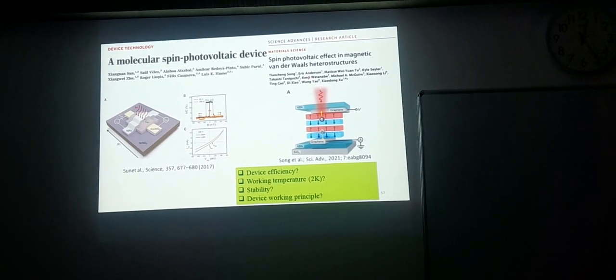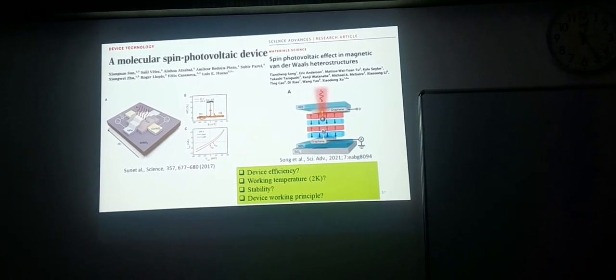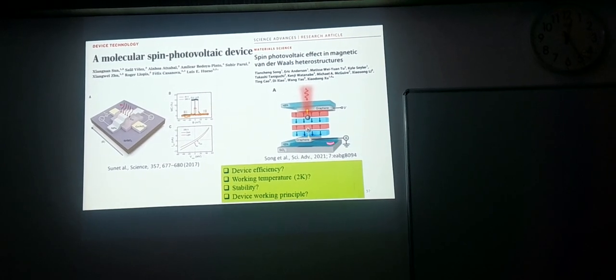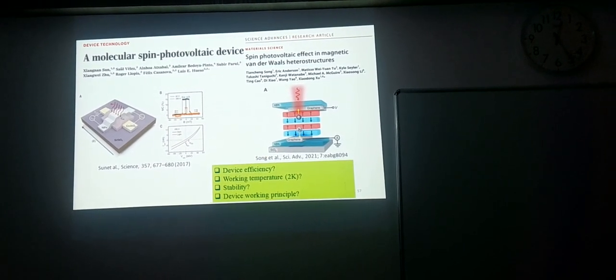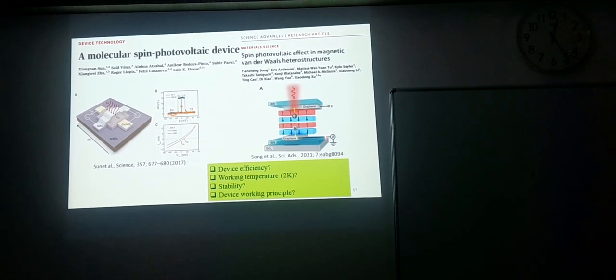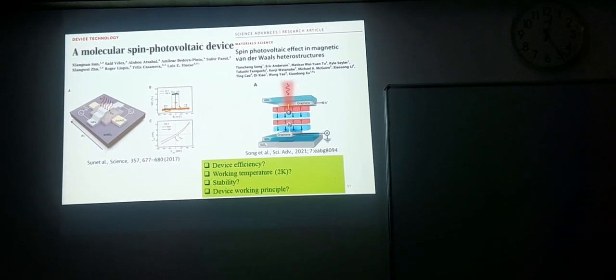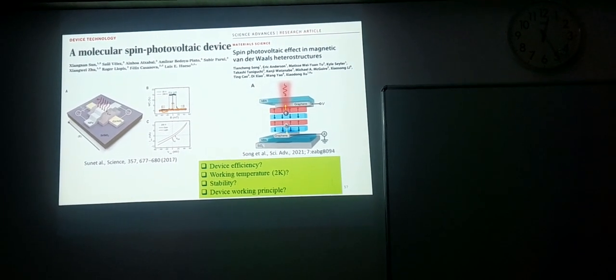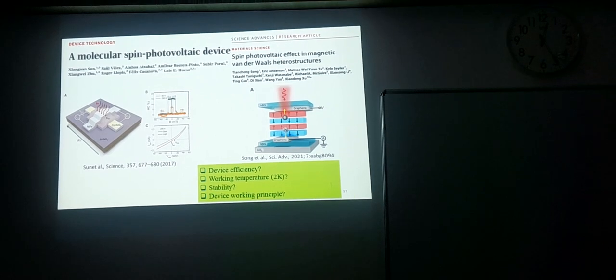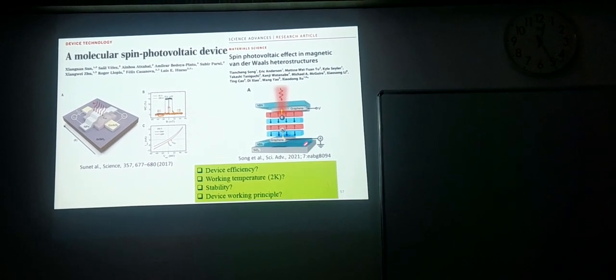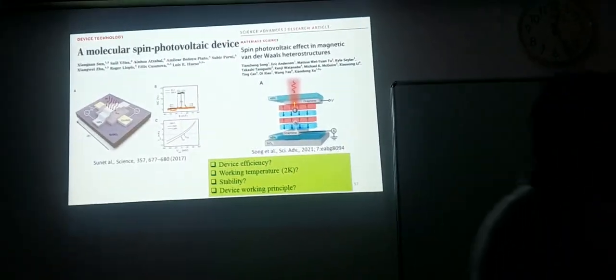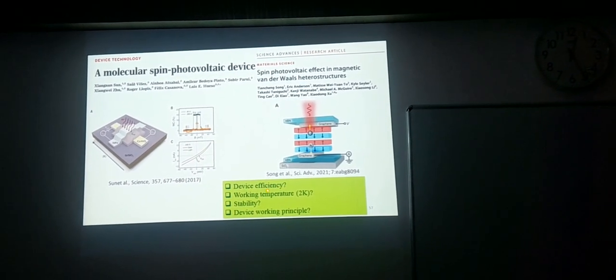Later, one group from the University of Washington showed this in a 2D material system. This is based on chromium trihalide, which I mentioned is a very unstable material, and they were able to show the same thing. If we have two different layers, the spins in each layer can interact with each other, and that can help generate charge carriers in the system. But all these devices work at very low temperature, less than 10 Kelvin. So our main motive is how we can improve this to high temperature, because the ordering temperature of this material is very low. That is one reason. But our functional materials have room temperature ferromagnetic properties. So we are focusing on understanding the device efficiency, working principle, and stability of these devices.